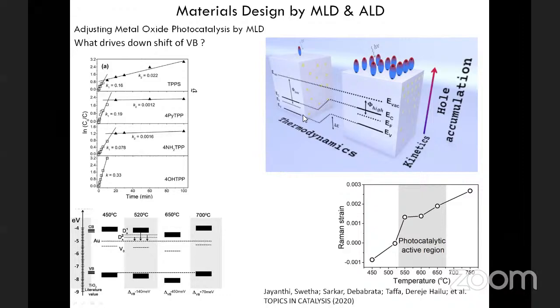However, you have to take into account additional effects, and these are the effects of the dipoles that form when you have a monolayer or a densely formed monolayer attached on the oxide surface, and this forms a shift of the work function. For tightly packed dipole monolayers, there is an upshift as a result of this packing, which costs you thermodynamically, again canceling some of the downshift that you had because of the internal strain. And the reason that our films can still break up such molecules is because, to begin with, we have an excess of almost half an eV downshift. So this effect cancels out and you can still have enough oxidation potential for the photogenerated holes.